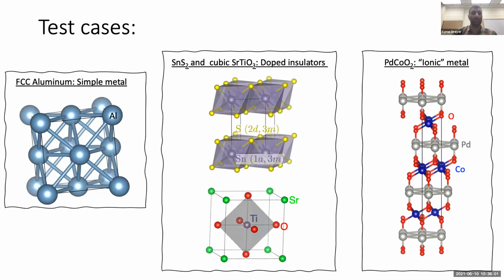Okay, so I'll show results for three test cases. The first is FCC aluminum, just a very simple metal. You should note that FCC aluminum has no optical phonon modes, so the physics of the Born effective charge are probably not that applicable in this case, but it's a good test of our methodology. Then we'll look at two systems that are insulating in their ground state, but can be doped. This will allow us to compare the Born effective charges in a conducting system, a doped insulator, with the insulating Born effective charges.